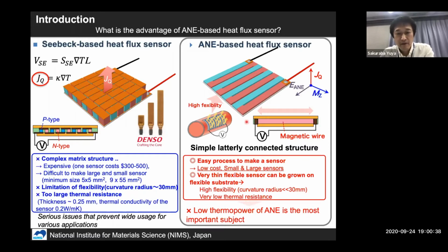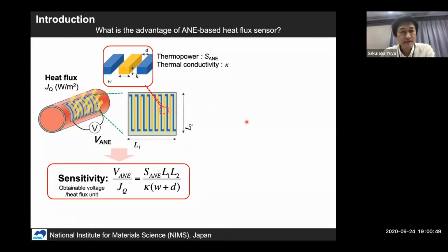However, as I mentioned, a low thermopower of ANE is the most important subject to realize this heat flux sensor. So again, to understand the required thermopower of the Nernst effect to realize the heat flux sensor, we performed a very simple simulation. Here we consider a rectangular heat flux sensor of length L1 and L2. And we put the magnetic material having width W and height H, and the distance between two magnetic materials is D. In this situation, the sensitivity of this heat flux sensor can be written by this equation here. S_ANE is the thermopower of the Nernst effect, and kappa is the thermal conductivity of the magnetic material.